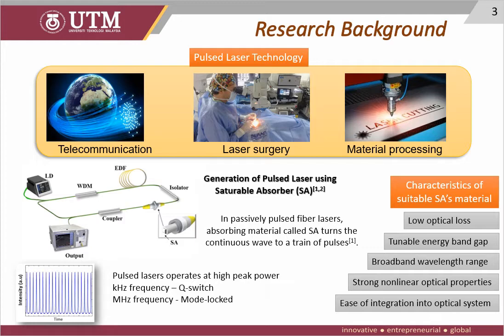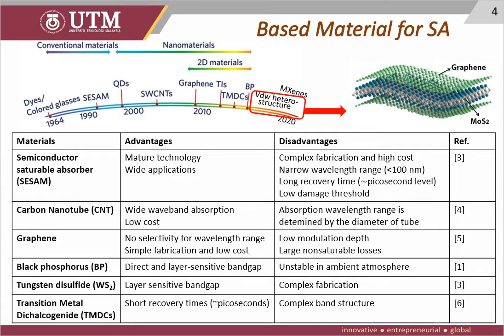The characteristics of a suitable SA material include low optical loss, tunable energy bandgap, broadband wavelength range, strong nonlinear optical properties, and ease of integration into optical systems. The evolution of the base material for SA starts with dyes, SESAM, quantum dots, carbon nanotubes, until the discovery of 2D graphene in 2004. There have been many ventures into other 2D materials such as topological insulator, TI, black phosphorus, BP, transition metal dichalcogenides, TMDs, MXenes, and many more. And they have shown successful numerous reports that use the material as the base material for SA.